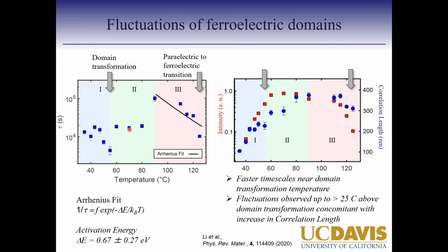So in these systems where you are used to thinking that the domains are forming because of the movement of the titanium atom, even at room temperature, we are seeing fluctuations in these domains. Now, we're not 100% sure if it's the domain walls moving back and forth that we are picking up, or if it's actually the domains. So for that part, it would be really nice to get some theory feedback. But in such solid state systems, these domains are showing a much softer nature.